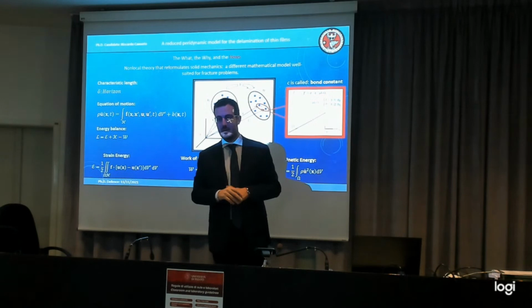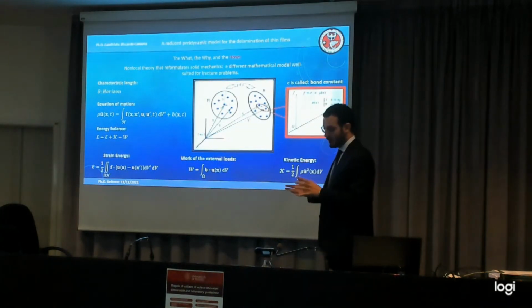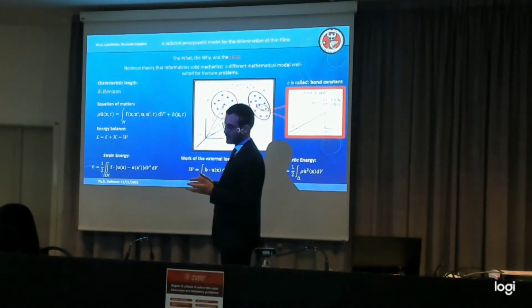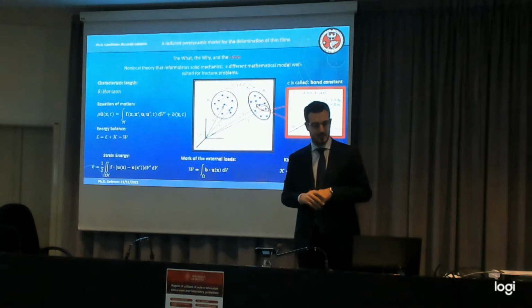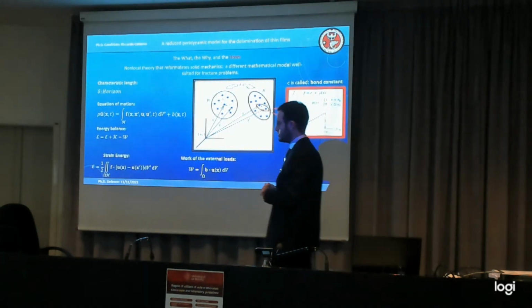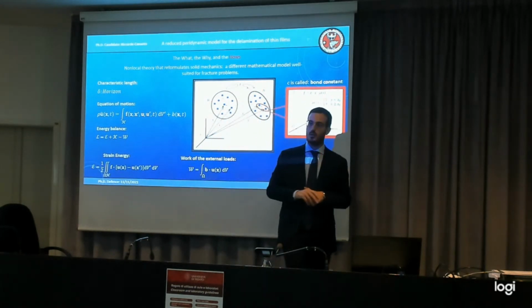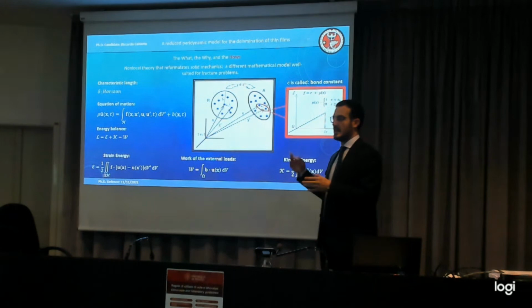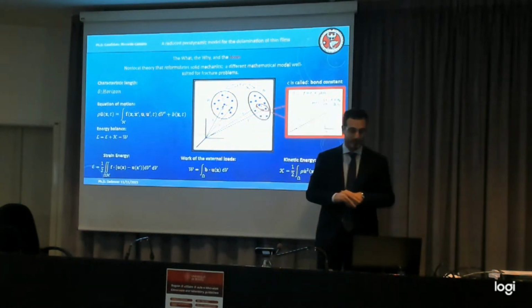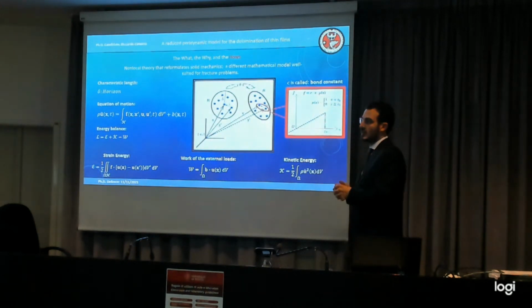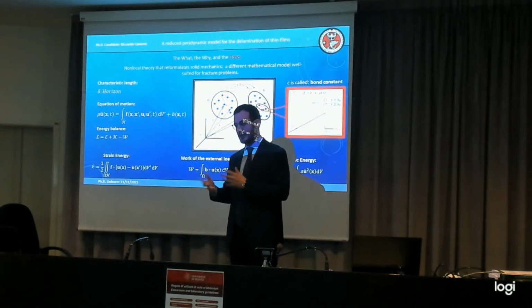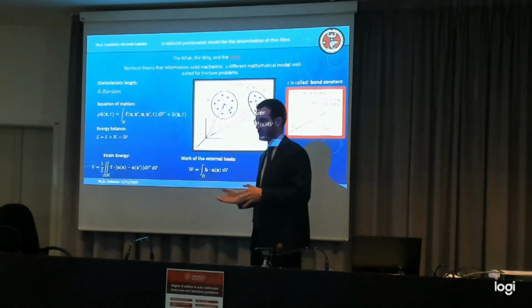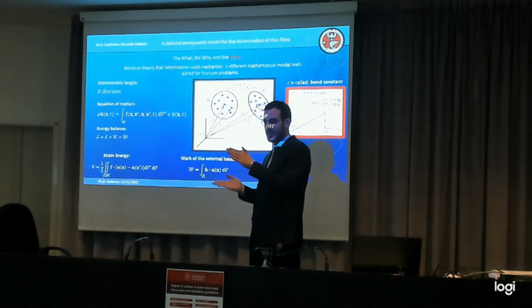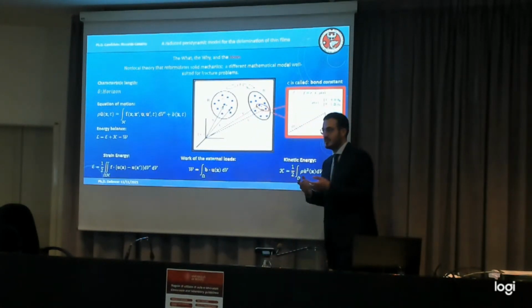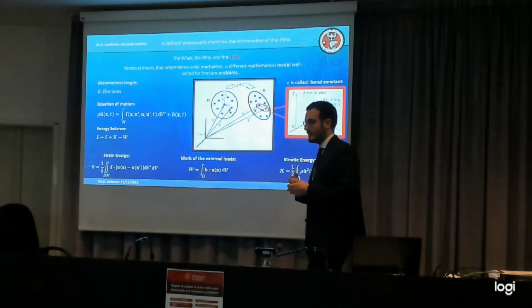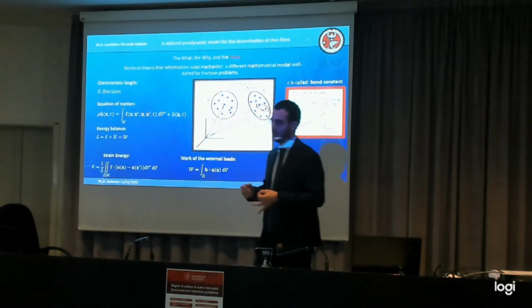All the materials that I've listed are sometimes made of or can be part of laminated structures. For example, airplanes have a lot of laminated structures in them, and there are present works that propose the solution of building lamps by using laminates. So there is a lot in that sense. And so for these non-local laminates, we need a non-local model to deal with a classical problem that can affect this type of structures, which is delamination. Delamination is a loss of continuity through the thickness of thin elements, and that can cause a high reduction of the performance of the material in terms of strength and stiffness.